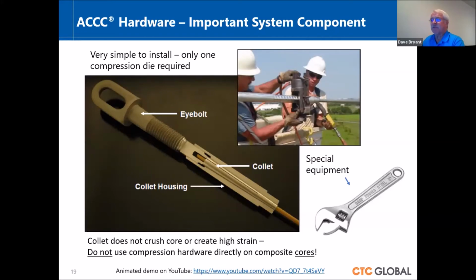Also, most dead ends and splices were designed to be fairly compact, and they don't have a lot of additional aluminum content. So these devices can heat up when the conductors are running hot. And the oxidation inhibitors that were used for ACSR conductor in particular really weren't able to handle high temperatures. So while some utilities will operate ACSR conductor and carry more amps on a hot day, when the temperatures might get hotter, there have been a number of problems with overheating of dead ends and splices.